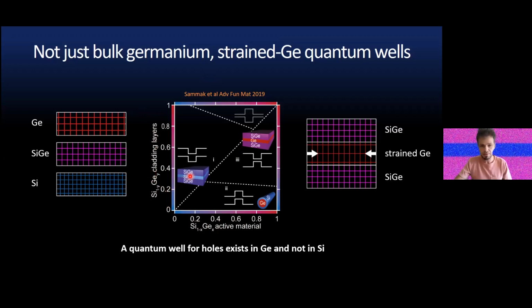Depending on the compositions, traditionally we worked with strained silicon quantum wells, where a tensile strained silicon, so 0% germanium, is on a SiGe 30% virtual substrate. And this has been used for electron spin qubits. What we've done instead is to move to the other side of the quadrant and work with a germanium-rich virtual substrate to then grow a pure germanium quantum well, which in this case will be compressively strained. Interestingly, a quantum well for holes exists only in this configuration in this diagram. If you think of silicon and germanium, this is the only configuration to have a high mobility two-dimensional hole gas.